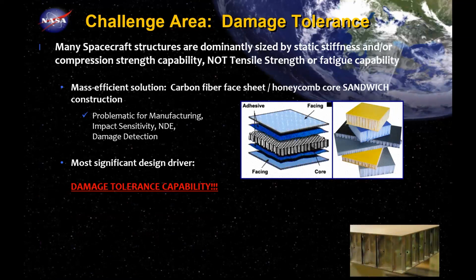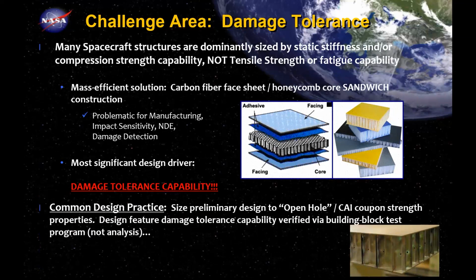So I told you earlier that we can't utilize that specific strength value that's up at the top of that comparison chart compared to aluminum or other materials, because we have to think about damage tolerance. And I consider this still to be our most challenging area in deploying composite structures into spacecraft. If you talk to the folks in aviation, they'll tell you the same. This is still at getting mass out of their structures. We do have more tolerance to damage than we do if it's designed by strength.